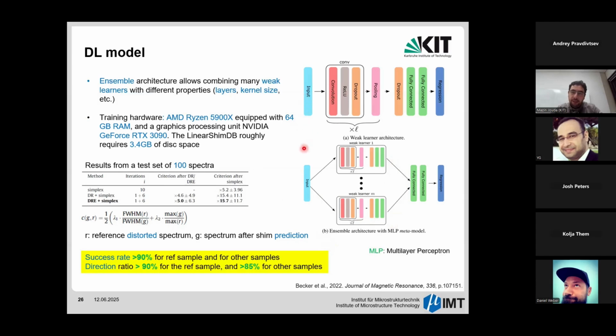We trained the neural networks, and then we tested them on a validation data set of 100 spectra. And we looked at both how much enhancement we get in the line width and how much enhancement we get in the amplitude of the spectrum. And we compared that to the simplex algorithm that is already applied in the spectrometer. So for the simplex, for 3 shims, it needs at least 10 iterations. And from 10 iterations, it enhances the line width and the amplitude by a factor of 5.